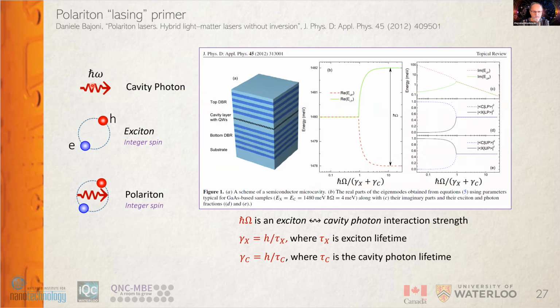So what you need is a cavity which can contain the photon, kind of try to trap it as much as it can. So typically they have double Bragg reflectors here, and your cavity here with excitons which are being generated either optically or electrically. And when you have enough interaction between the exciton and cavity photons, then they create another quasi-particle, which is the polariton. And those are pretty decent quasi-particles, as it turns out.